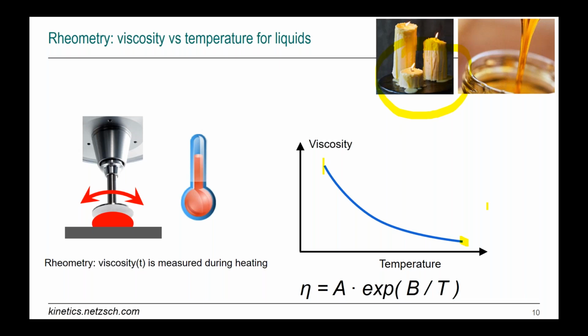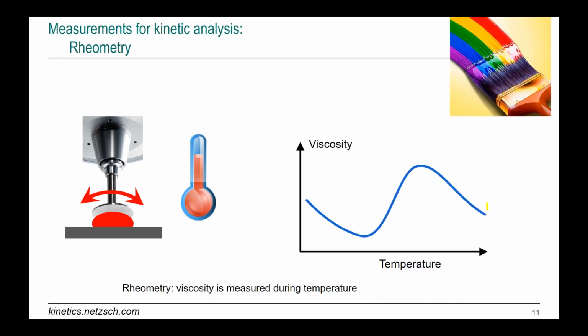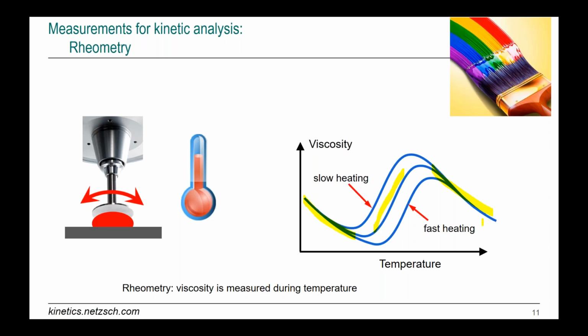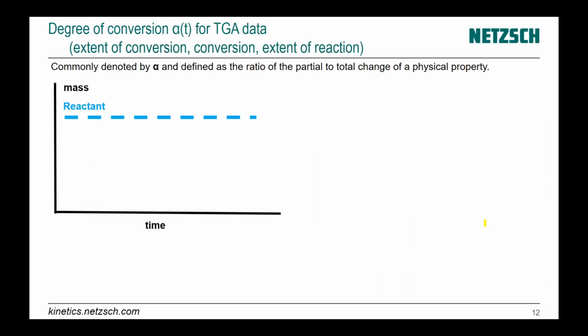If there are chemical reactions—for example in adhesives, paints, or epoxy—the viscosity curve looks like this: decreasing for the reactant, decreasing for the product, and increasing in between during the reaction. We can run it fast or slow, and we see the result depends on the heating rate.